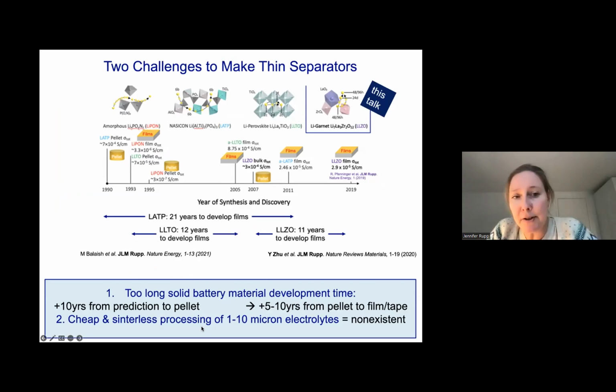And that's something we have also looked at a bit. And you can see here the major lithium solid state electrolytes in their categories. So there's LiPON, LATP, lithium lanthanum titanate perovskite, and lithium garnet. And what's surprising is how long our field needs to get a pellet, for instance, in a laboratory that can't be transferred to industry into the right performance spec of conductivity and electrochemical stability window, and then to make a film structure out of it, just make it thinner.